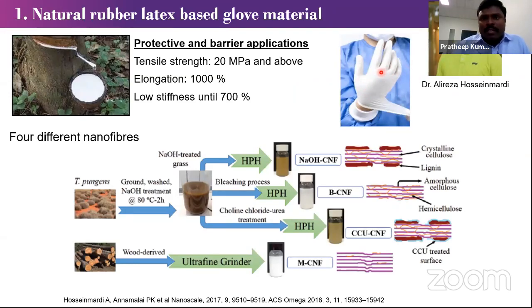For gloves, you need really thin material. You don't want to make really thick gloves. You want to make it thin, but it should have strength, and also flexibility so that you can really wear it, with a good touch and good feeling. So you want softness in this material. With natural rubber, you can make it strong by chemical cross-linking, but you don't want heavy chemical cross-linking and a thicker material. So you can use nanomaterials, unlike other inorganics. This nanocellulose would be better because it's thinner and more sustainable.